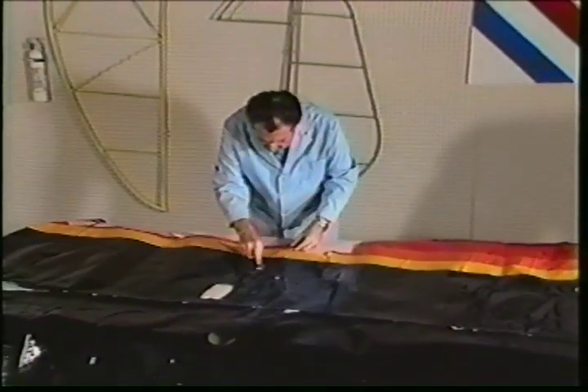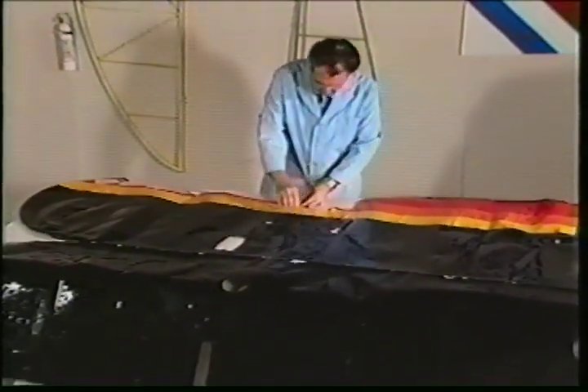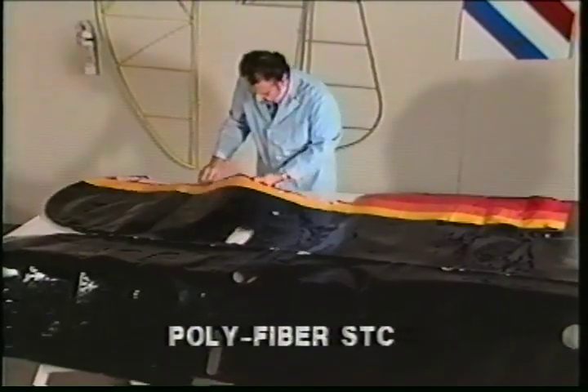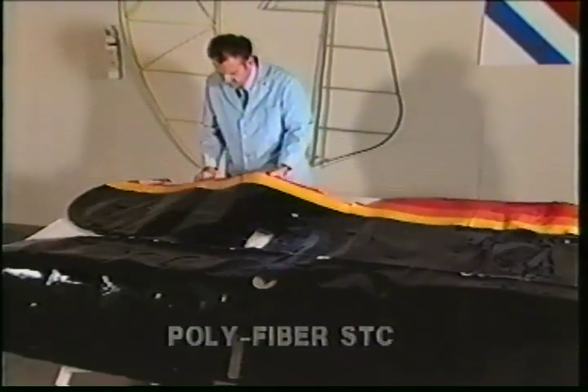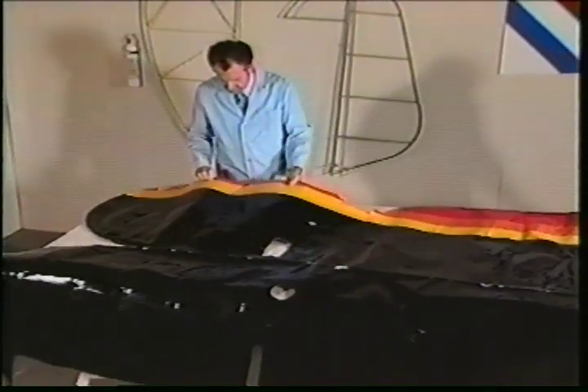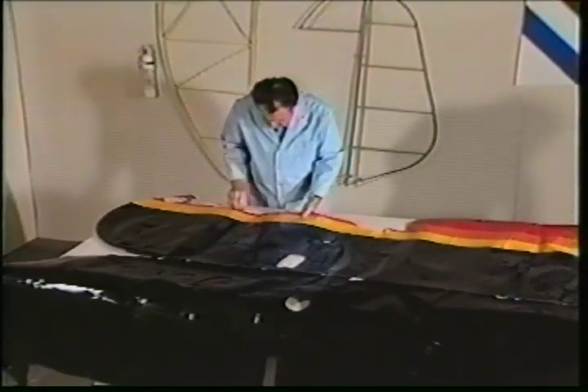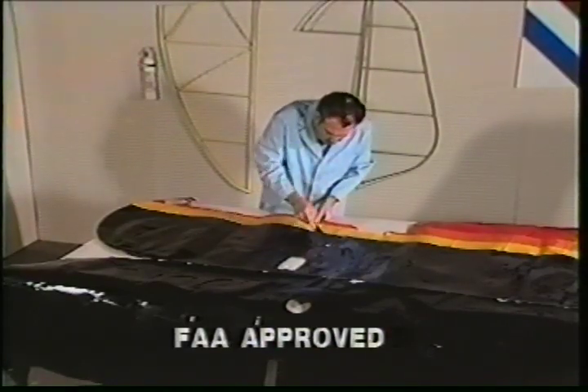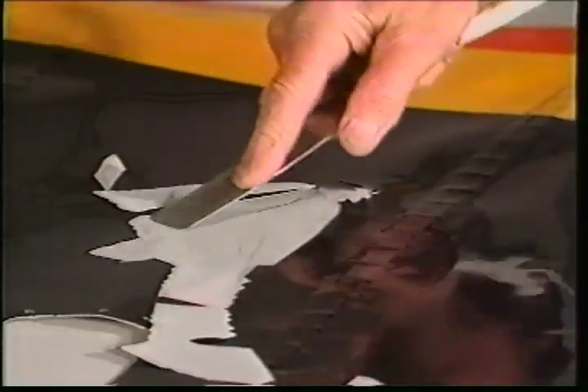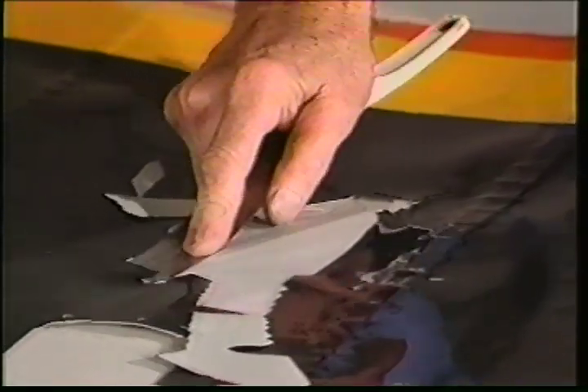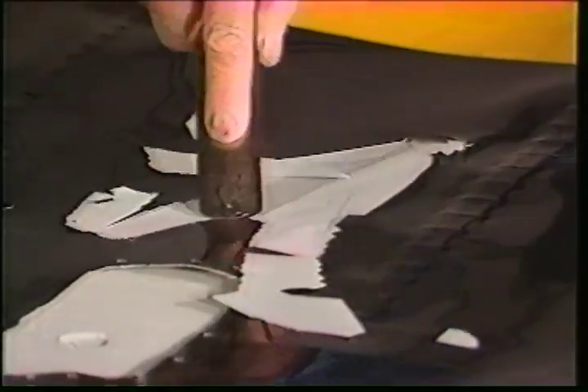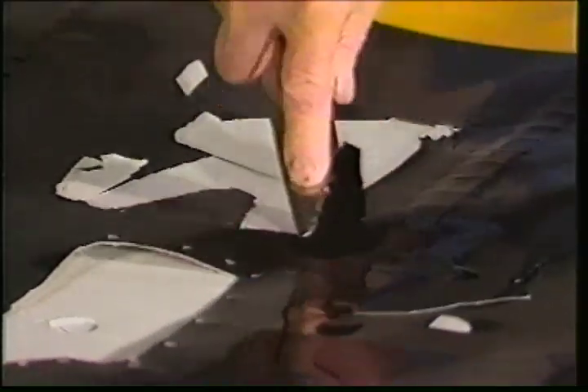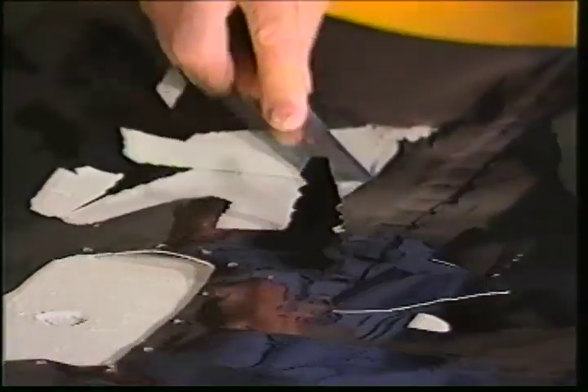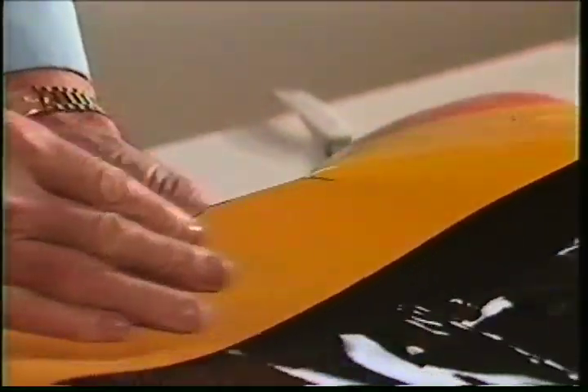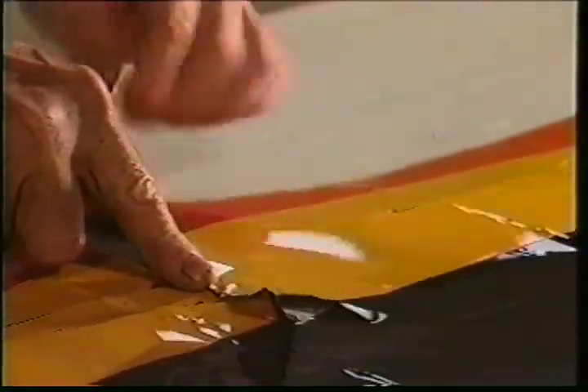This 6-month-old wing covering is off an aircraft that was recovered and put back into service using the Polyfiber STC number. And according to the records and logbook, only Polyfiber materials were used. However, this fabric is coated exclusively with an FAA-approved polyurethane primer and finish, and its characteristics are typical of all brands of fast-drying, high-gloss, acrylic-based polyurethane coatings competing for the automotive repainting market. The finish and subcoat are brittle at room temperatures and become even more brittle as the temperature drops. When the coatings are flexed, they snap like glass and peel off with less resistance than nitrate dope, leaving the